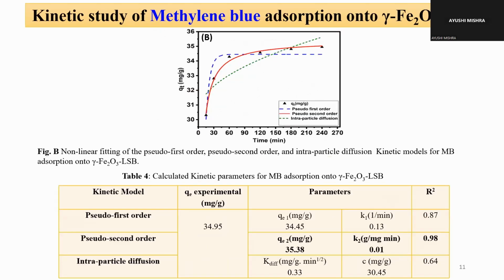We have also performed the kinetic study of the adsorption process, in which it followed the pseudo second order kinetic model. The experimental Qe value, the adsorption capacity, is closer to the calculated Qe value, and the R square is also 0.98. So we can say it follows the pseudo second order kinetic model.